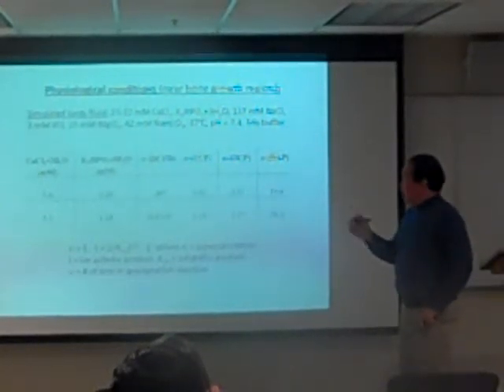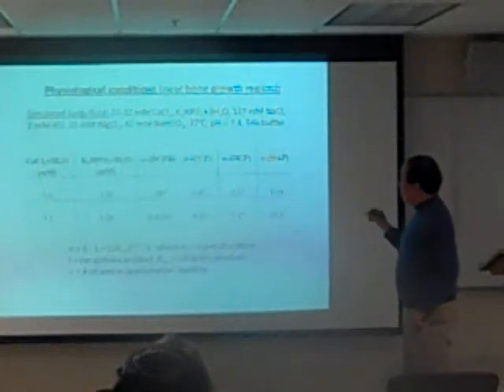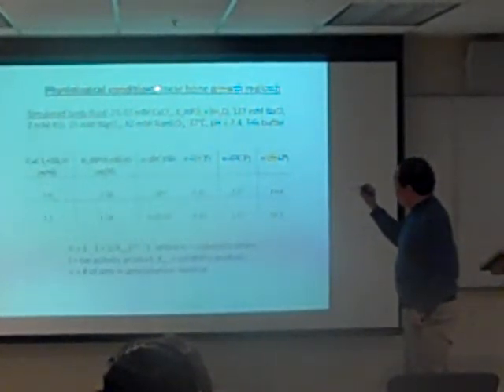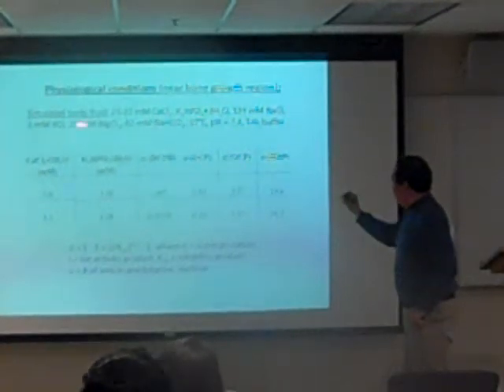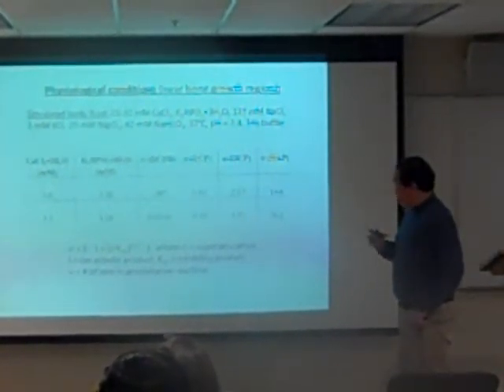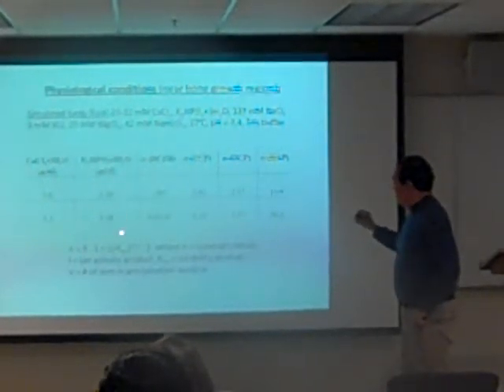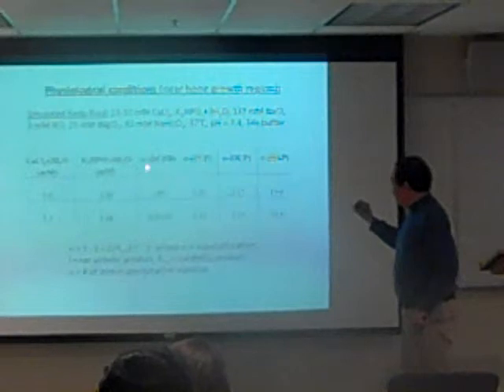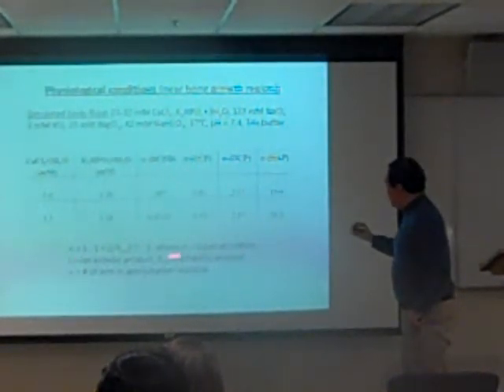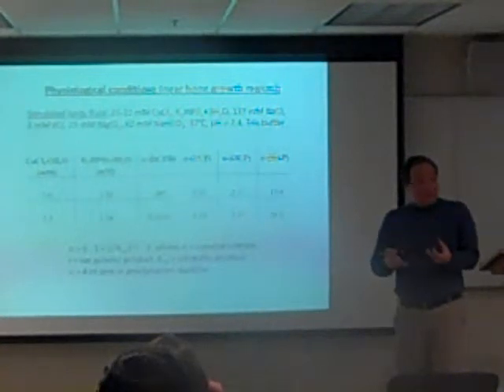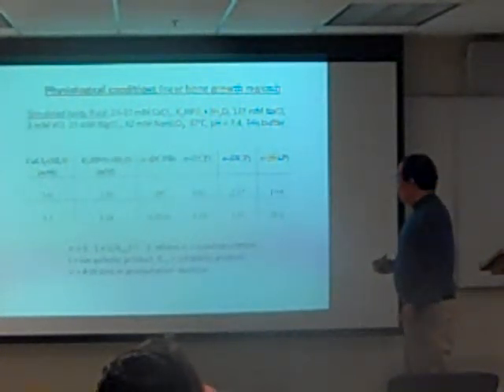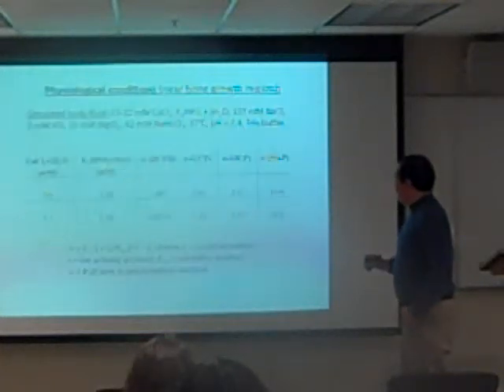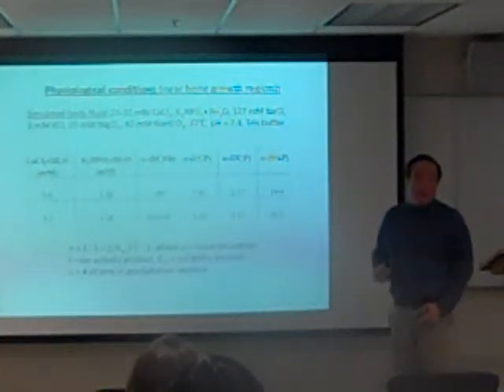So what we did is we took the self-assembled monolayers and immersed them in solutions that mimic physiological conditions. This favors the growth of the different calcium phosphate phases. These are the concentrations that were used. This sigma here is a parameter that was adjusted such that certain phases will grow, will appear. And of course, that was determined theoretically based on this model. So if we adjust the solution parameters here, we can try to grow these different phases of the calcium phosphate.